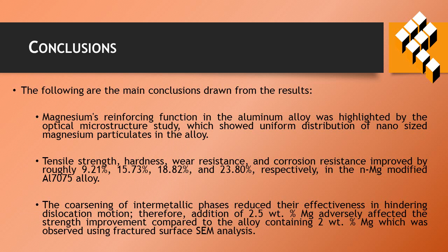Conclusions. Magnesium's reinforcing function in the aluminum alloy was highlighted by the optical microstructure study, which showed uniform distribution of nano-sized magnesium particulates in the alloy. Tensile strength, hardness, wear resistance, and corrosion resistance improved by 9.21%, 15.73%, 18.82%, and 23.80% respectively in the nano-sized magnesium modified aluminum 7075 alloy.